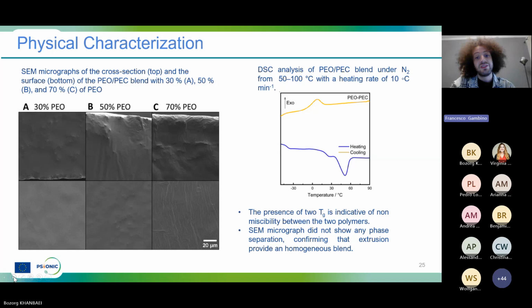However, from DSC measurement on the right image, there were revealed two distinct Tg of the polymers, indicating that there is no miscibility and that the microphase separation is present at the submicronic scale. Next slide, please.